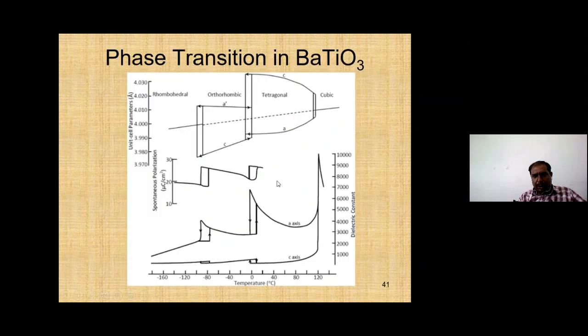So these are the high temperature region we are dealing with. This is the dielectric data of the same sample. This is the value of the lattice parameter for the same sample. As you can understand, this particular setup which we have designed is for high temperature measurements. It doesn't apply to this low temperature part. So you can see that when you perform this dielectric measurement, there is hardly any hysteresis. In fact, these are along different directions, but even if you measure in the heating cycle and cooling cycle, there is very small hysteresis.